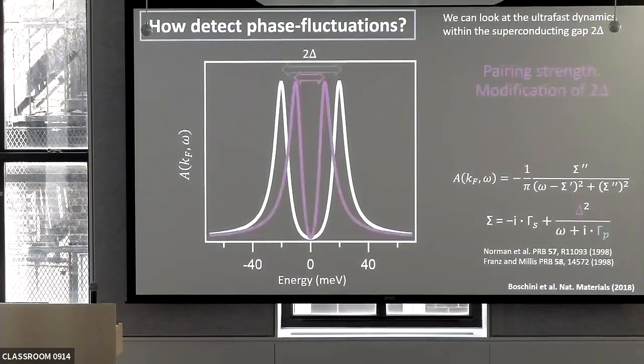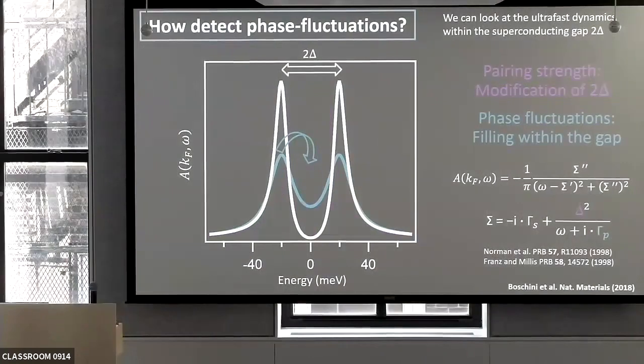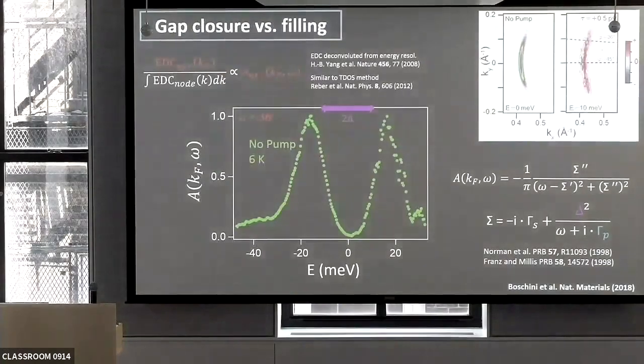Now when you pump it, if you modulate the pairing strength, delta, then simply the two peaks move close to each other, the gap gets smaller and nothing else changes. If on the other hand much of the action is in gamma, so in the broadening, in the phase fluctuation, then the peaks would basically stay in the same place, but they broaden out and spectral weight is transferred within the gap. So the two scenarios would be gap closing versus gap filling, related to pairing being the key parameter in controlling superconductivity, or phase fluctuation in the other case. And here is the experiment.